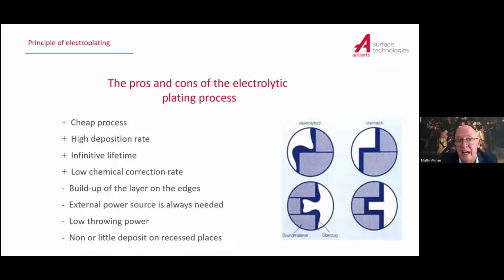It has an infinite lifetime. What we do is you plate in the tank, your nickel is dissolved from the anode, so it keeps on coming back, so you don't have to do anything about it. The only thing is what you drag out when you take parts out, so you correct that with some chemicals, but for the rest, the tank stays working. You clean it once a year and you can work in it. So we also have no chemical correction rate.